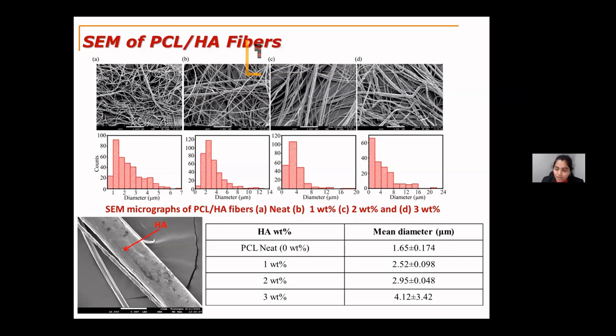So this hydroxyapatite particularly has a tendency to agglomerate itself very soon. It absorbs moisture very soon. I tried 2 minutes in the thinky mixer, planetary mixing of the nanoparticles for 2 minutes, 3 minutes, 4 minutes, 5 minutes. I tried to vary the time while mixing. However, for higher weight percentages, these particles once mixed get deposited at the bottom of the solution and agglomerate there. So again we need to mix it to inject the solution to generate the polymer nanofibers. So that is what I meant by agglomeration of the particles.